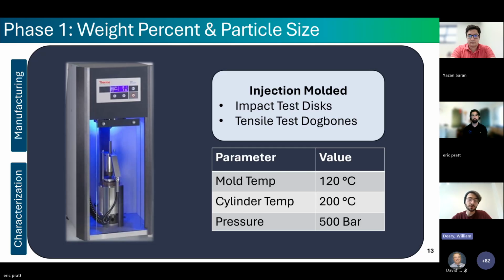From each of our 16 formulations, we molded type 4 tensile dog bone specimens, as well as impact test discs. We did notice during our processing studies that the compositions which were approaching 40 weight% became much more difficult to injection mold, and we had some incomplete mold filling as well as bubbles occurring in the part. Once again, this was a lab scale observation that helped us inform our future scale-up trial. In total, this stage of the project produced over 200 individual dog bone specimens, along with hundreds of impact discs, which gave us a robust and statistically meaningful data set to carry into our characterization.